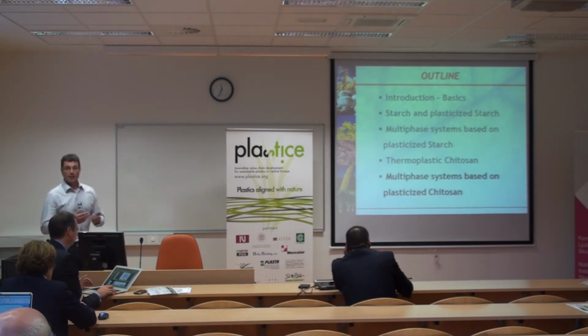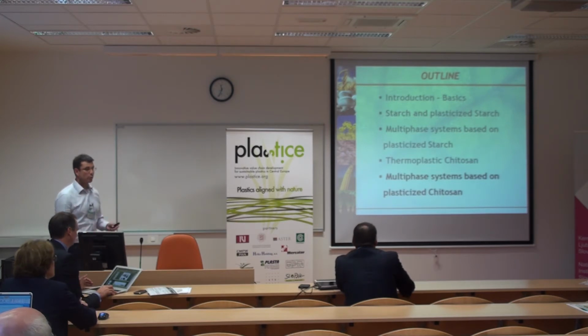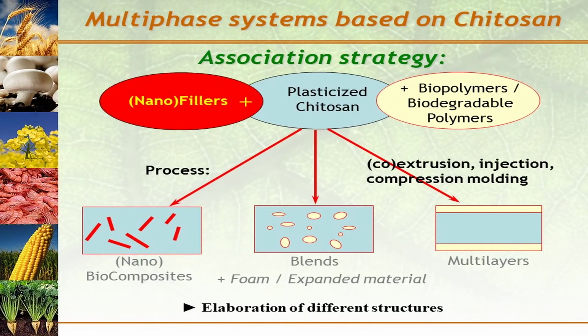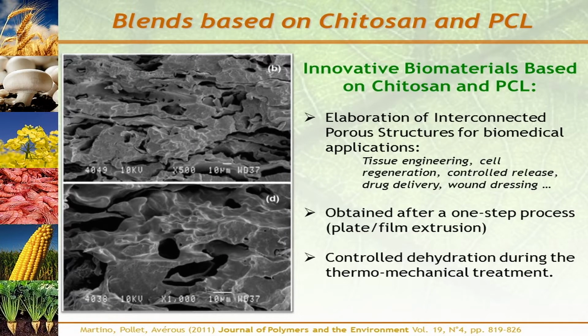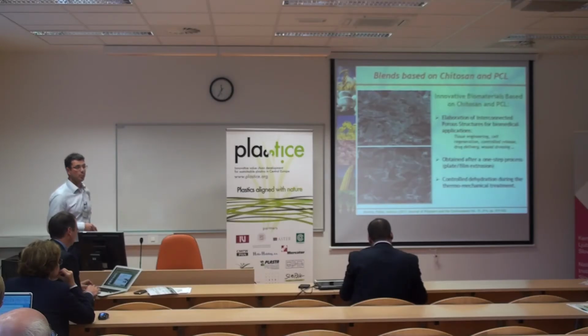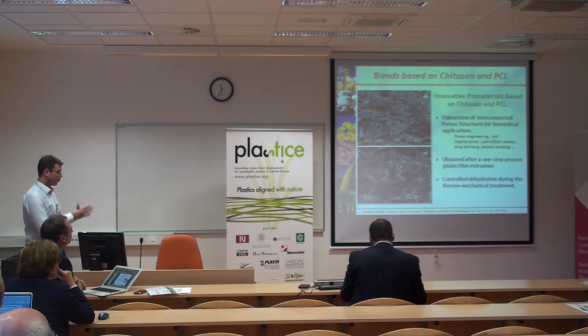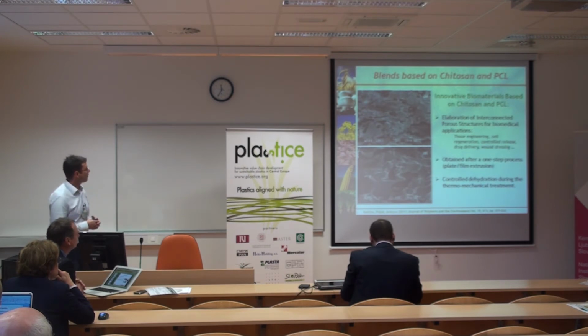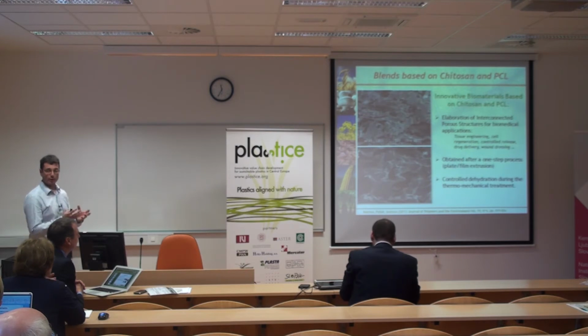So with this plasticized chitosan, we have also tried to develop multiphase systems, trying to improve some of the properties of the materials, always using the same strategy. I will show you an example of blends and then nanocomposites based on plasticized chitosan. On blends, we have tried to make blends based on plasticized chitosan together with polycaprolactone, PCL, and it was extruded with PCL. And due to water evaporation, all the water contained in plasticized chitosan evaporates during the processing, leading to a porous structure that could be interesting for biomedical application that have not been tested and studied so far.